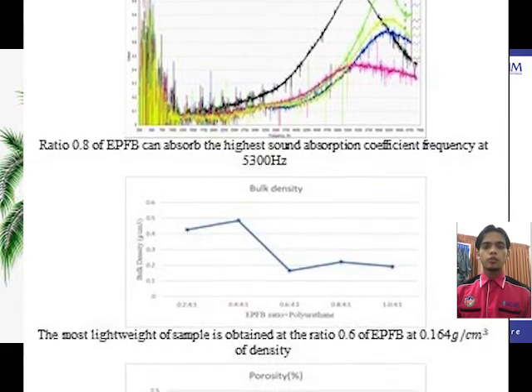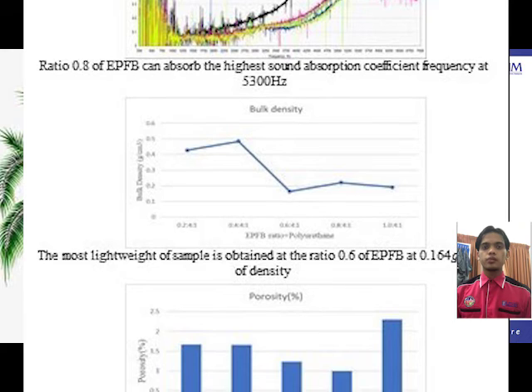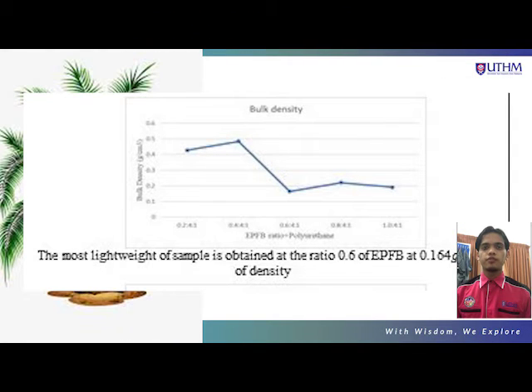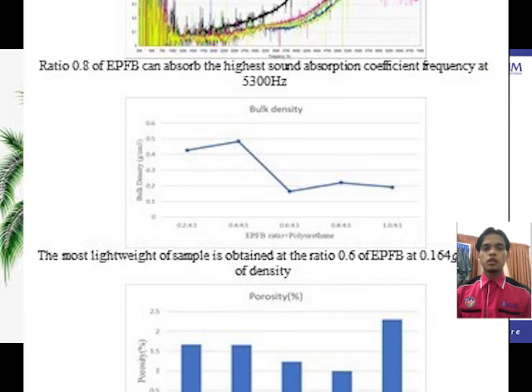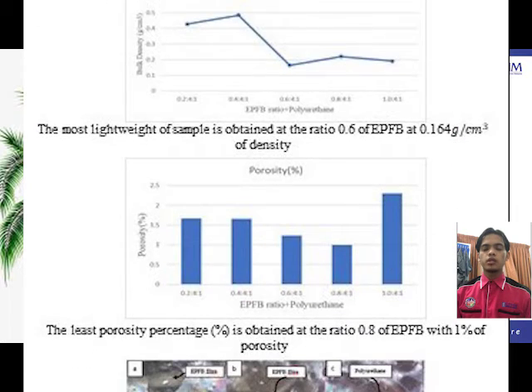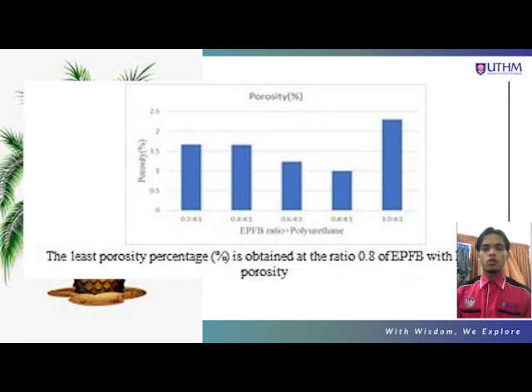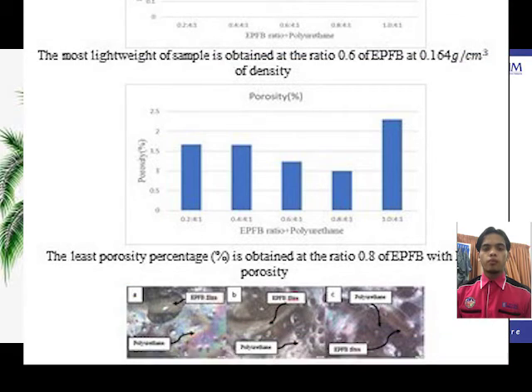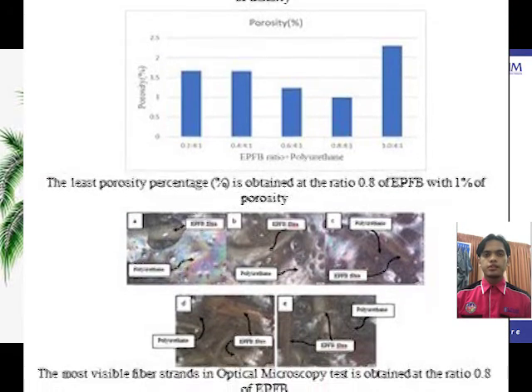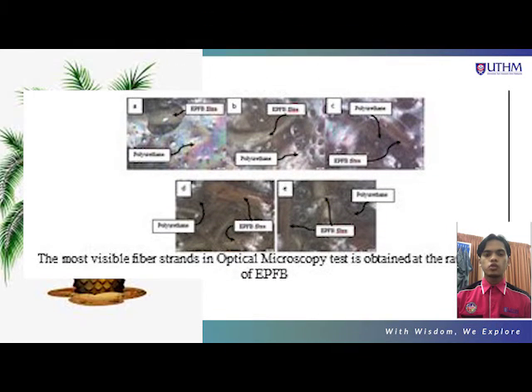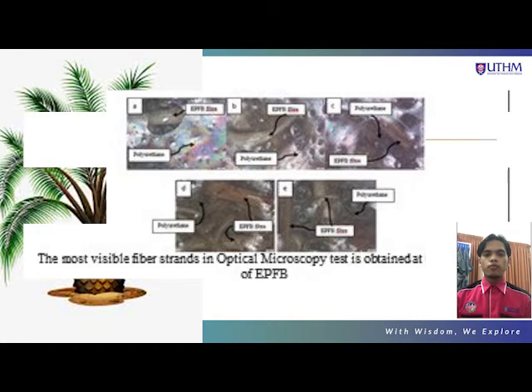For its physical properties, the most lightweight sample is obtained at the ratio 0.6 of EPFB at 0.164 gram per centimeter cube of density for the density test. For the porosity test, the least porosity percentage is obtained at the ratio 0.8 of EPFB with 1% of porosity. For the optical microscopy test, the structure for ratio 0.8 of EPFB is the most visible and has strong composite bonding between the PU and EPFB fiber.